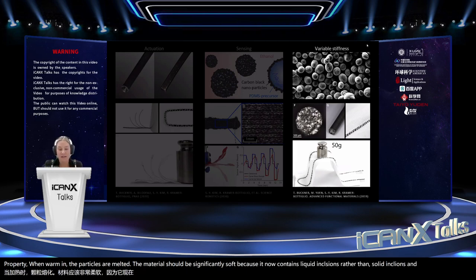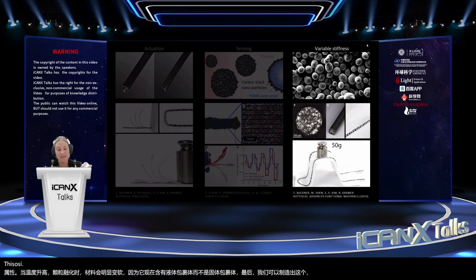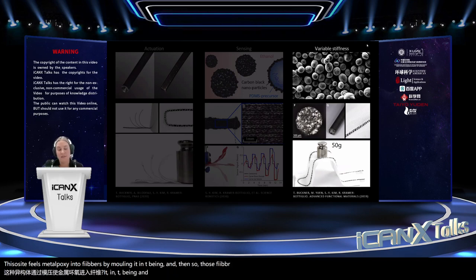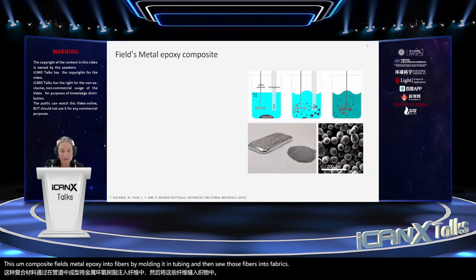And finally, we can fabricate this composite Fields metal epoxy into fibers by molding it in tubing and then sew those fibers into fabrics. Okay, so we set out to fabricate these low melting point alloy particles, specifically selecting Fields metal, which is a combination of indium, bismuth, and tin, and has a melting temperature around 62 degrees Celsius.